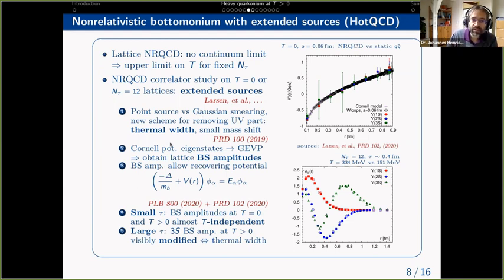Then the authors extended this work. They started to use operators that were modeled after Cornell potential eigenstates. Then they used the so-called generalized eigenvalue problem to optimize, by linear combinations, the overlap with the real eigenstates of the QCD problem, and obtained lattice Bethe-Salpeter amplitudes. Once you have these Bethe-Salpeter amplitudes for at least two different states, in this case the Upsilon 1S, 2S, and 3S, you can feed these into a Schrödinger equation and determine the pole mass and the potential, because you know these amplitudes and you know the energies.